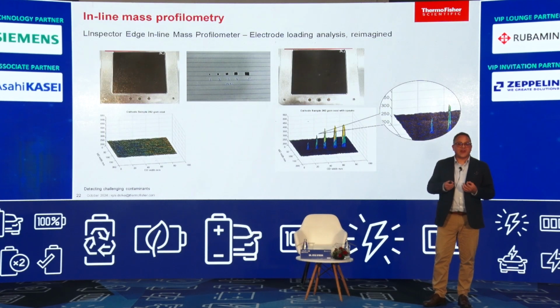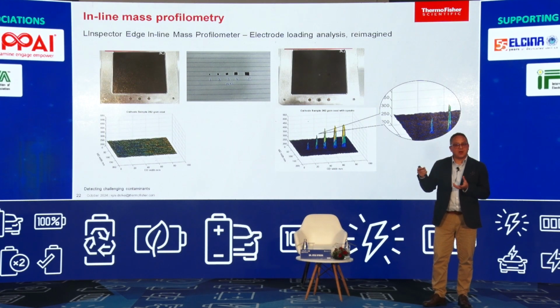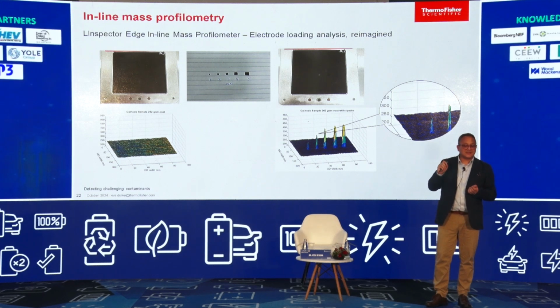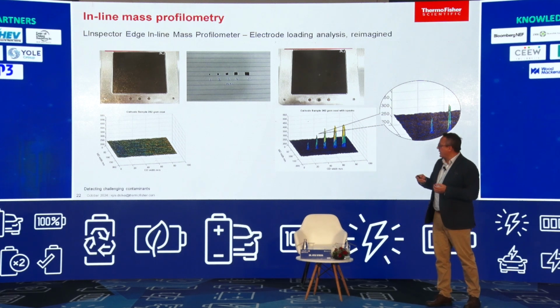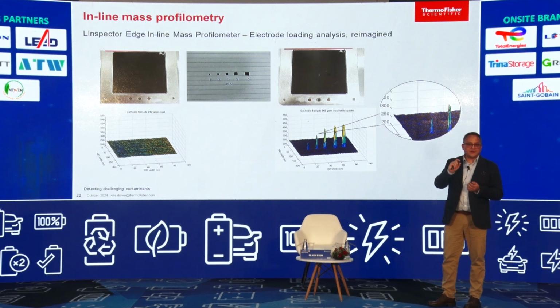Here's an example of flakes, material that is broken off and it's dropped back onto the electrode. Here you can see very small flakes down to less than a millimeter, and the machine can detect this at, again, 100 meters per minute. Very easily, this is cathode active material on top of cathode active material. Small flakes, very difficult to see.